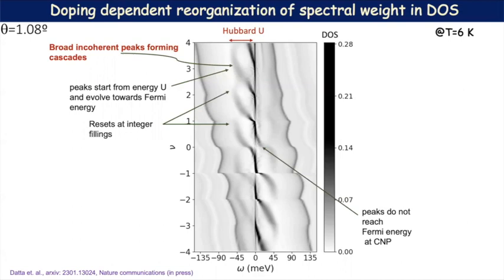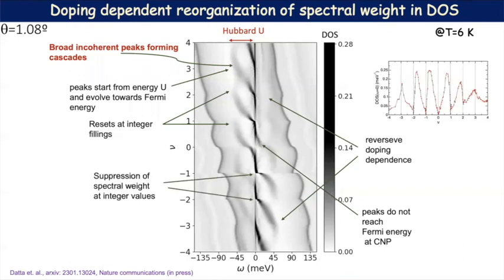And this happens for all the integers except at zero doping, where the peak does not reach zero energy, but drifts away, avoiding this point in this way. And we have reverse doping dependence, as you can see here. This one has the maximum weight on the negative energy, and this one has the weight on the positive energy. You can also see that there's non-monotonicity in the spectral weight at zero energy. So we can see that there is suppression of spectral weight at the integer values.